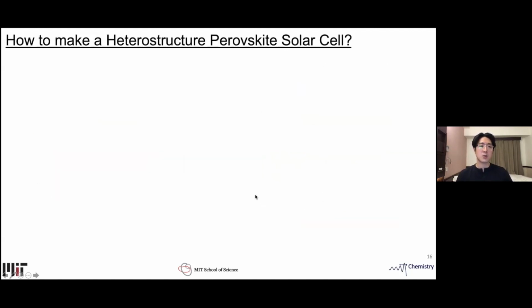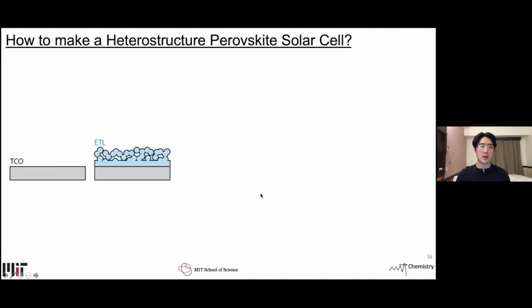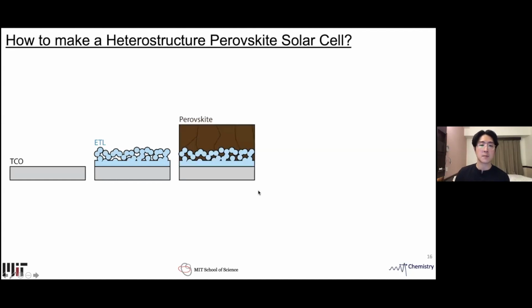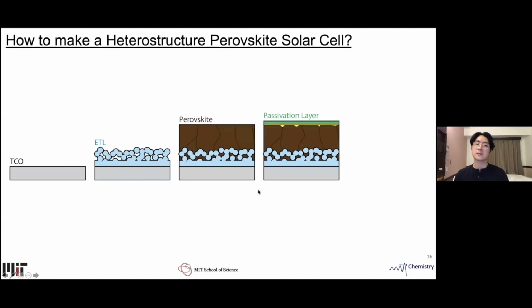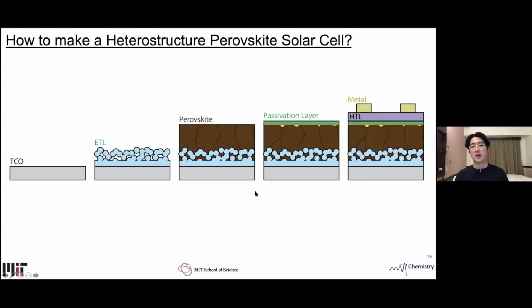So then how does one go about making such a device? We would first start with a transparent conductive oxide, followed by deposition of the electron transport layer, the perovskite layer, the passivation layer, and finish off with the hole transport layer and the metal contact.